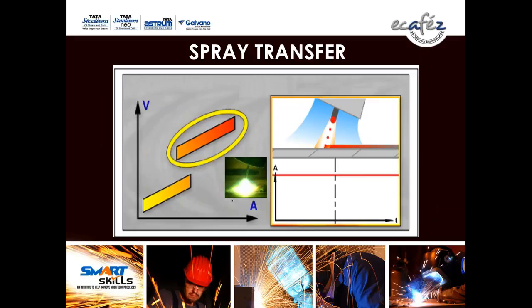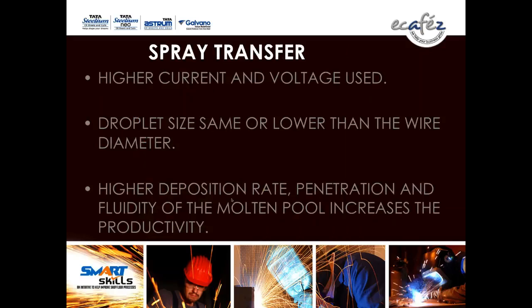Spray transfer, like a spray of water, will give you the best results. Higher current and voltage can give you spray transfer. It is the best transfer in the MIG process. Droplet sizes are the same as or lower than the wire diameter. Your wire diameter is 1.2 or 0.8. If the droplet size is lower, then your quality of weld will be finer. Higher deposition rate will be available. Penetration will be very good. Fluidity of the molten pool increases the productivity by using spray transfer.